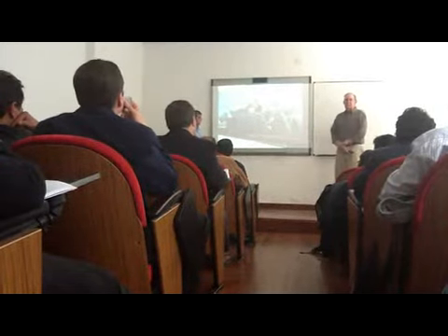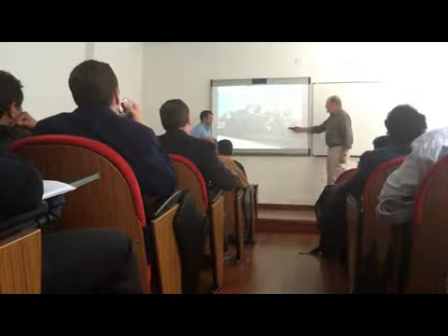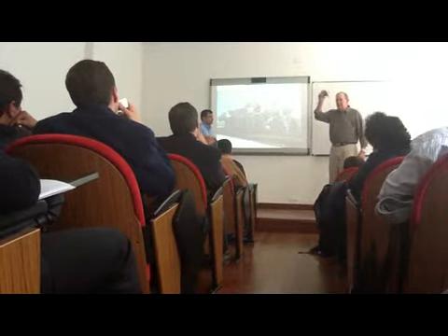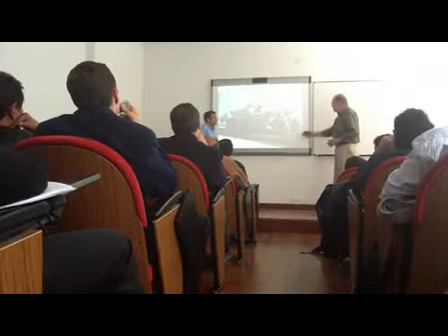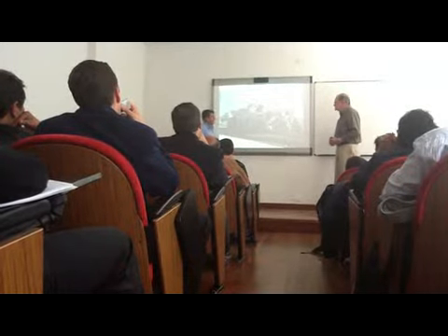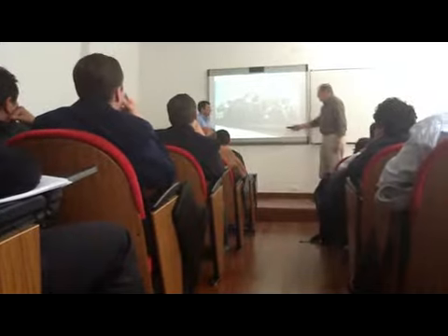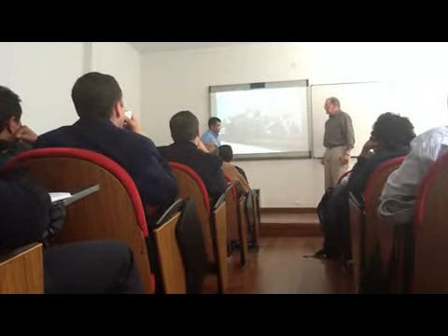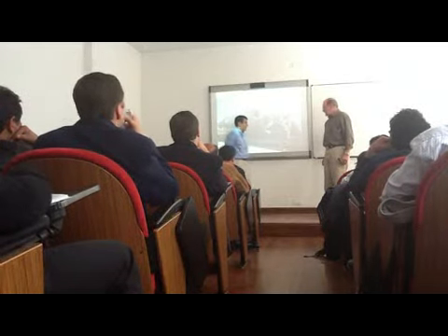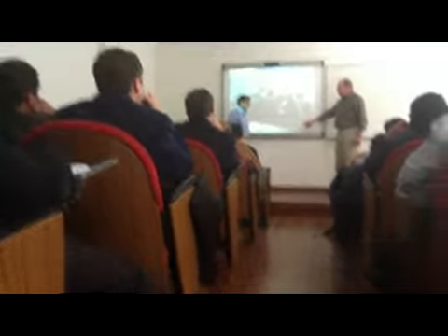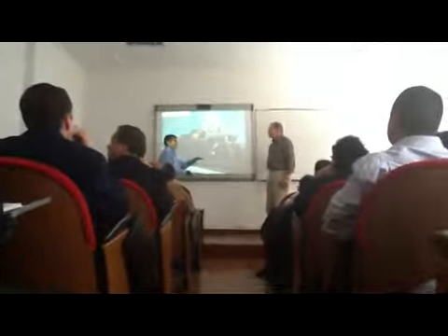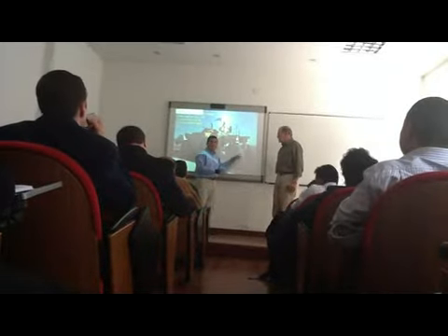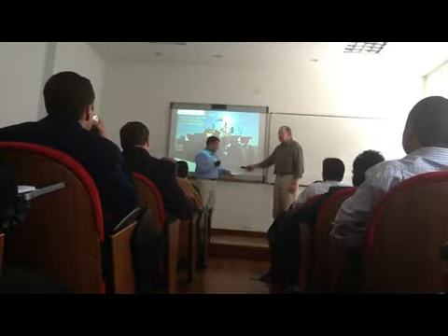Here is the machine that I was describing to you before. This is the machine that is actually doing the mixing and putting the moisture and the polymer catalyst into the material here. And it mixes to the extent that the gradation of this material, the top size, has to be 90% minus an inch and a half screen. And 65% minus number 4.